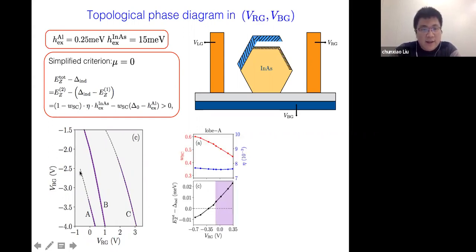So for example, in this lobe A, when we tune the right gate from negative to positive, we see that this magnetic efficiency eta does not change much. But the hybridization, or the weight in the superconductor, dips monotonically when you increase the right gate voltage. And that means for the particular subband mode, more of its wave function now is inside the indium arsenide nanowire, and less wave function in the aluminum. So the direct Zeeman energy will increase because more wave function is inside indium arsenide, and the induced gap is less. So that caused the topological quantum phase transition in this evolution.